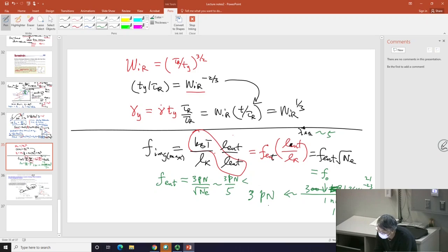This is less than 1 piconewton, and even this F0 is only a few piconewtons. When I say only, I really mean something very remarkable. Not very much, because for the chain to break, the force involved is several, let's use 3, is 3,000 piconewtons. So there's a factor of 1,000.